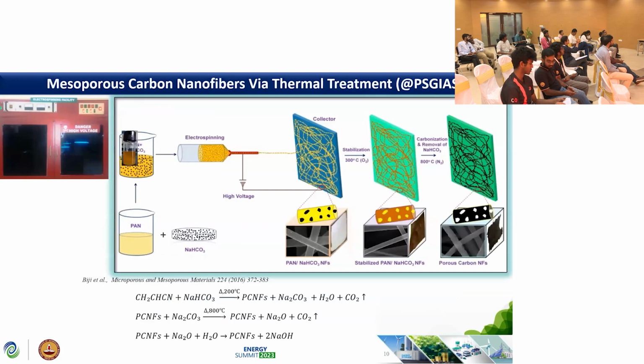Coming to the methodology we are adopting, we have specifically formulated one methodology to create intentionally induced mesoporosity in carbon nanofibers using electrospinning. In electrospinning, we force the polymer solution through conductive needles connected to a high voltage source. Because of this high voltage, the polymer fibers split into nanofiber structures. To introduce mesoporosity, we used polyacrylonitrile as the precursor and introduced ball-milled sodium bicarbonate nanoparticles in the size range of 2 to 50 nanometers. We blend these sodium bicarbonate nanoparticles into the polyacrylonitrile solution and use that as the feed solution for electrospinning.